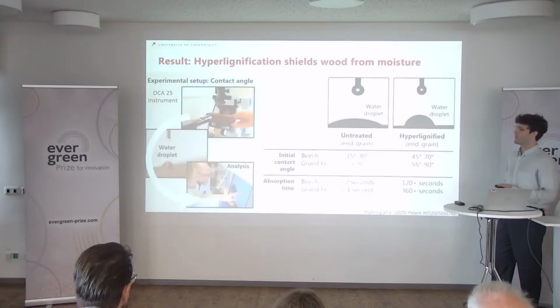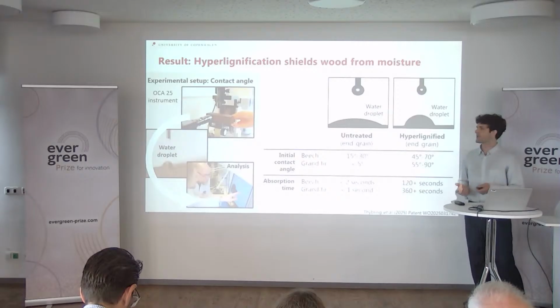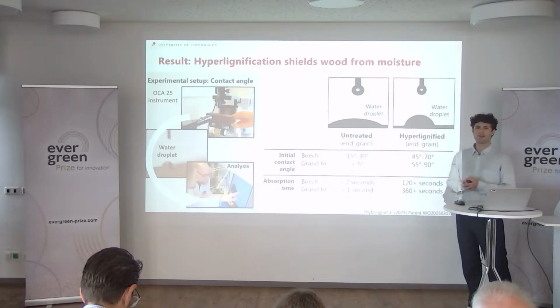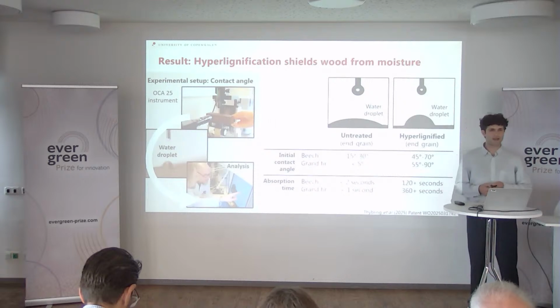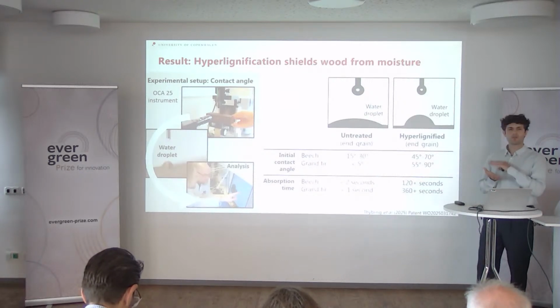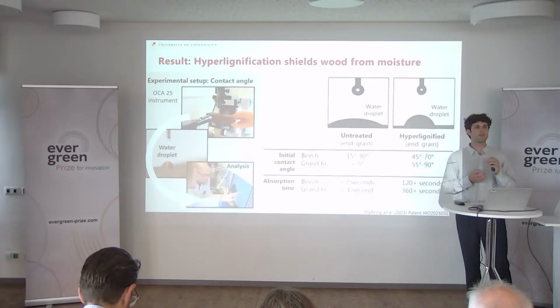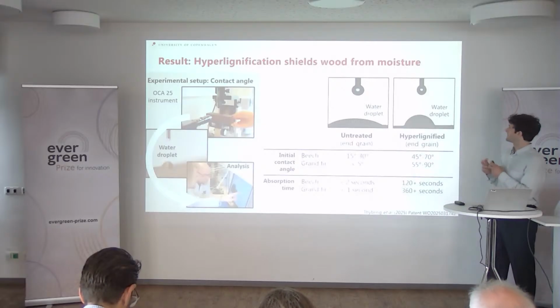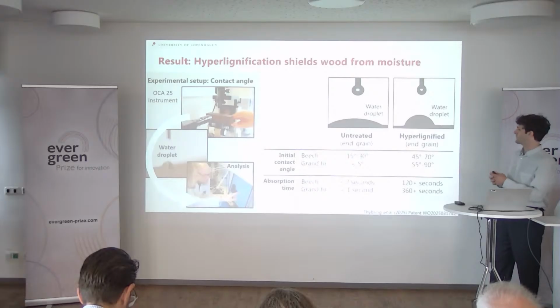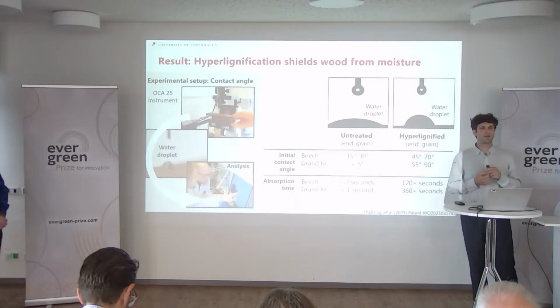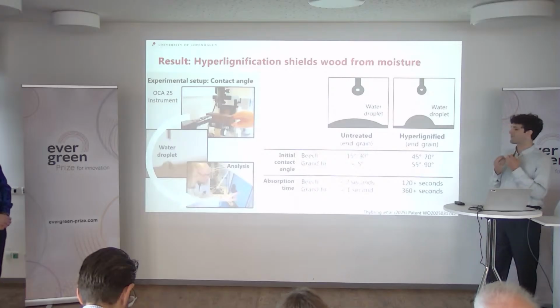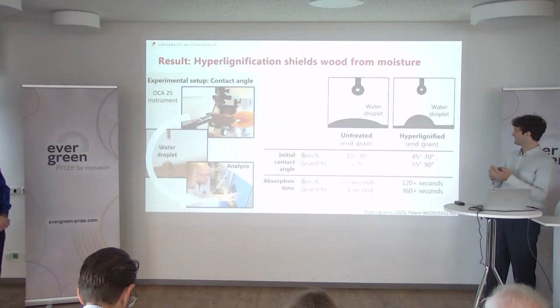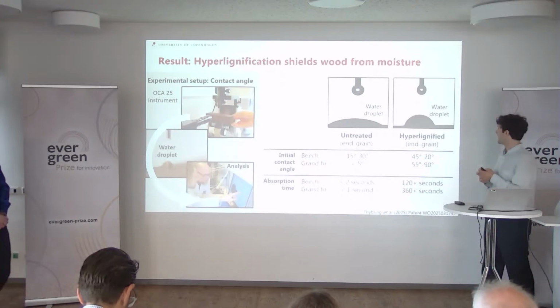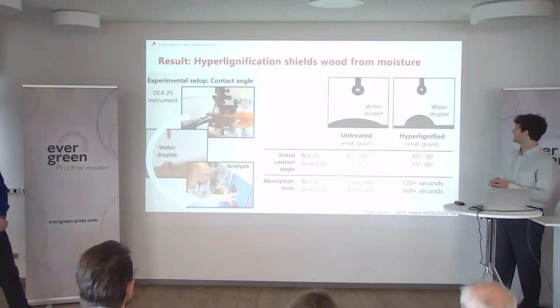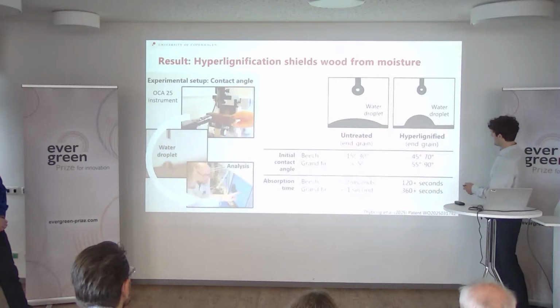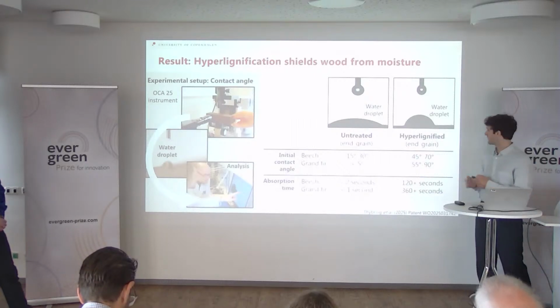So then we wanted to know how this would affect the properties. And one of the key properties we wanted to address was hygroscopicity. So we used water contact angle, and we exposed the cross section, which is the section that most readily absorbs water, of our samples, both untreated and hyperlignified wood. And we saw that the droplets we were dropping on the surface were readily absorbed by the untreated samples within 1 to 2 seconds, while for the hyperlignified wood, it takes minutes to absorb, so the surface energy is lower.